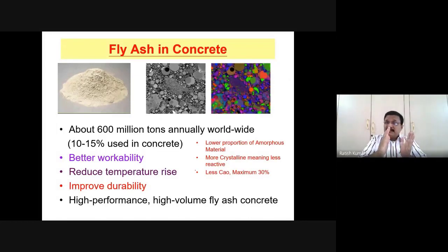But the point here is the reaction is going to be slow because it has a lower amount of amorphous proportion. So that's the reason why we get a late gain in strength. More crystalline means it is less reactive. So my recommendation is go for 10, 15%, 20%. At the maximum, you can try to go for 30% in case of fly ash.